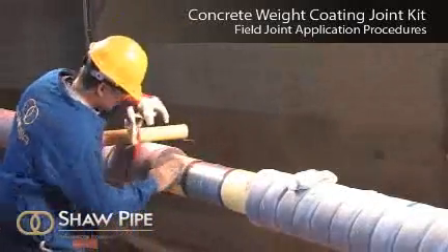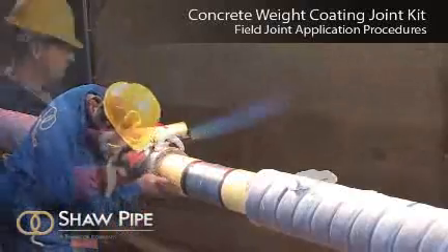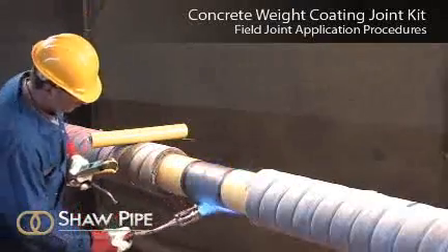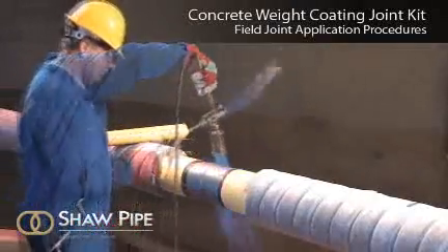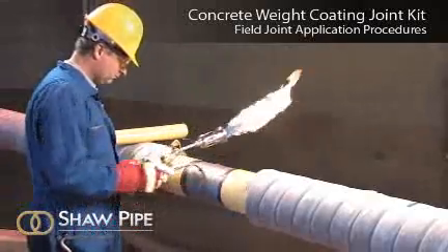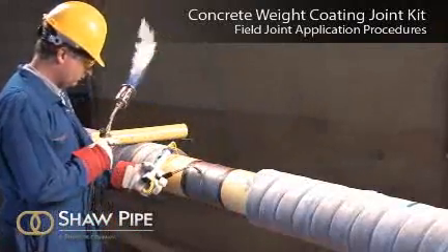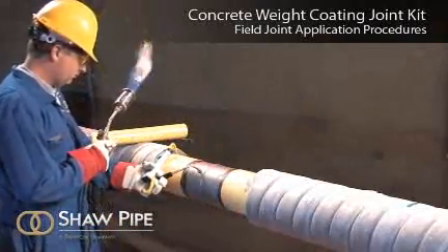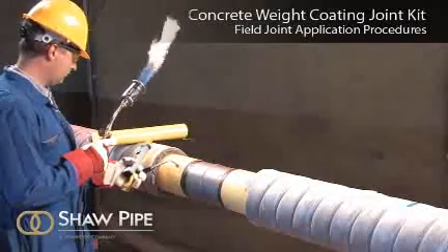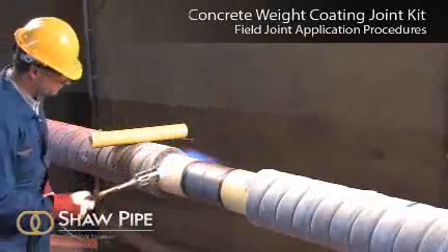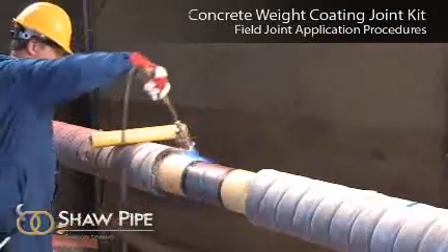The K60 Rapid Sleeve requires preheating of the steel surface and adjacent mainline to at least 65 degrees Celsius or 150 degrees Fahrenheit. This is done so the adhesive will melt and flow on contact. This enhances adhesion for long-term performance.